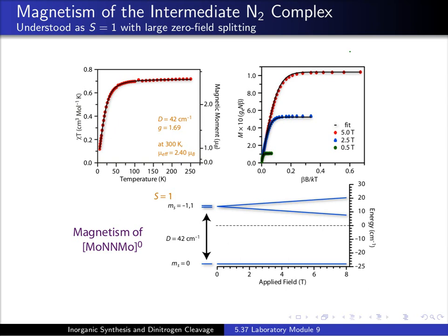Those two unpaired electrons in the purple bridging N2 complex intermediate give rise to interesting magnetic properties that we've been able to study as a function both of temperature and also as a function of the magnetic field, allowing us to assign an S equals 1 ground state to that bridging N2 complex intermediate. So that's S equals 1, that's a triplet state with those two unpaired electrons. I won't say too much more about that.